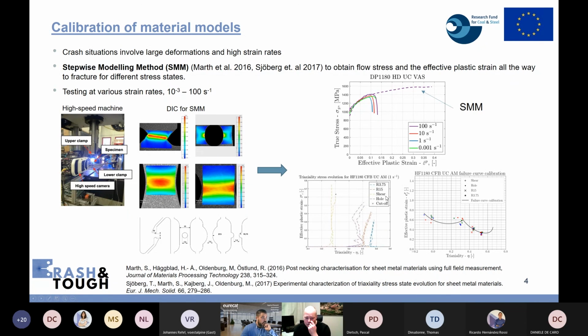Yeah. So, could you please quickly repeat the question? I was asking if you have noticed a relevant effect of the strain rate on these flow curves and the fracture strains obtained for the steel grades, at least in the range that you investigated. Yeah, you could see this is an example. Okay, yes, you have some hardening because of the strain rate, but it's not very high. And when it comes to the failure strains, we concluded that we couldn't see any dependency on the strain rate for a certain specimen geometry, at least in our range, from 1 to 100 per second.